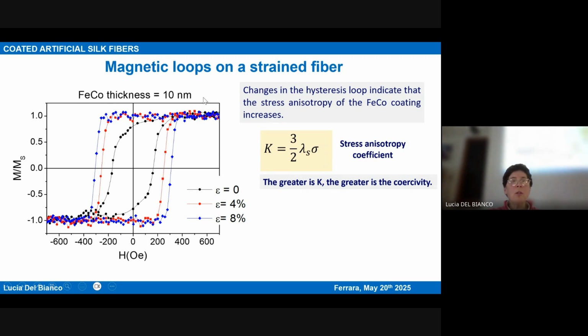For instance, on the fiber with iron cobalt 10 nanometer thick, you see three different hysteresis loops taken at different values of the strain: 0, 4%, 8%. And you clearly observe that the hysteresis loop is changing. In particular, the anisotropy, the coercivity is increasing. And this happens because by stressing the material, stress anisotropy appears in the fiber.